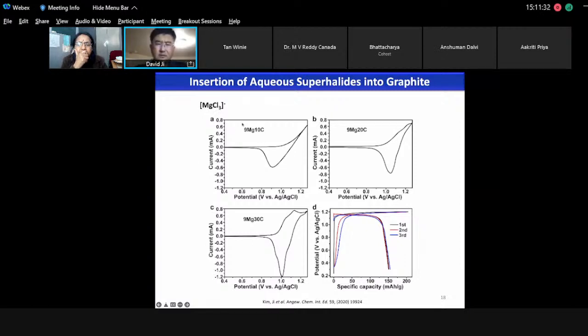And again, we designed different electrolytes. And here 9 means 9 molality magnesium chloride, 10 means 10 molality choline chloride. Then we increased the concentration of choline chloride, and we started to have this redox behavior. We have a lot of chloride. Magnesium, we have no choice but to form this superhalide.